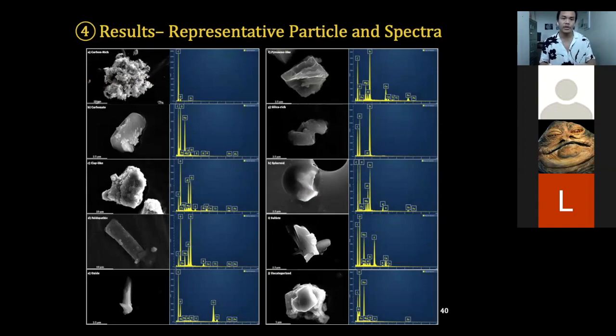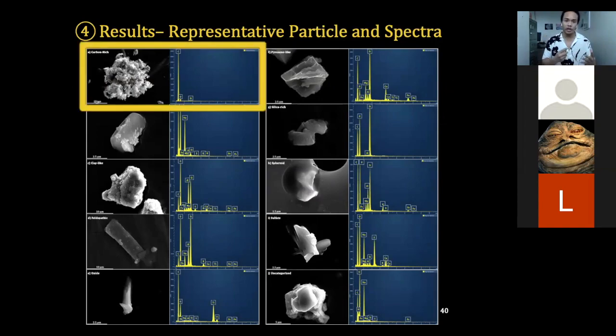Now just going over representative images and particle spectra of each of the categories that we found in our two samples. So again, here's an image, and then to the right of them are just spectra, which gives us the elements that are present, and then the height of the peaks tell you the relative abundance compared to everything else. Starting with carbon-rich. So the carbon-rich particles ranged from having a morphology that is pollen-like or little spheres. For this particular example, it has a graphitic or graphite-like texture. And looking at the spectra, you can see that there is a high carbon peak and not really much of anything else.